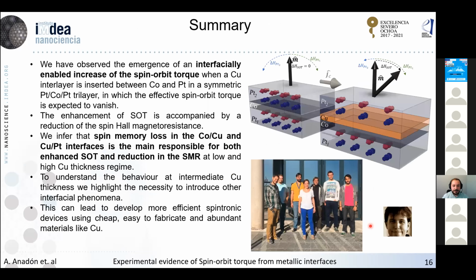So basically, the message that you should take away from this talk is that we have observed an interfacial enabled increase of the spin-orbit torque by introducing a copper interlayer in between cobalt and platinum in a symmetric platinum cobalt platinum trilayer. This enhancement of the spin-orbit torque comes with a reduction of the spin-Hall magnetoresistance that gives us information on the origin of this increase of the spin-orbit torque, and we infer that the spin memory loss is the main responsible for this enhanced spin-orbit torque and this reduction of the spin-Hall magnetoresistance.